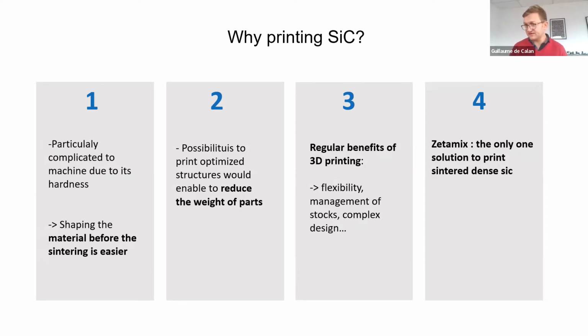Shaping the material is quite complex, and clearly if you want complex shapes, you really need to do them before sintering, because machining the material after sintering is literally horrible - it's so hard. So it's very, very hard to machine after sintering, so you need to do everything before. That means if you want very complex parts, it may be difficult with silicon carbide to obtain these. You will usually do silicon carbide by pressing and green machining, and that will limit a bit the kind of geometries you can do with silicon carbide.